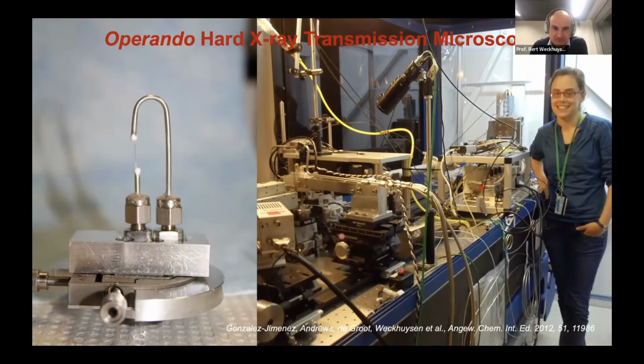Now, it sounds trivial, but I just show you here one of the challenges. Here I show you a very tiny capillary which contains the catalyst particles. And here gases come in and gases go out to a mass spec. And this device is put here. And this rotates, and at the same time gets gases over it. And this is a heater which can be brought down with these screws. That means that by doing this, you can now bring this under pressure, under temperature, and do catalysis.